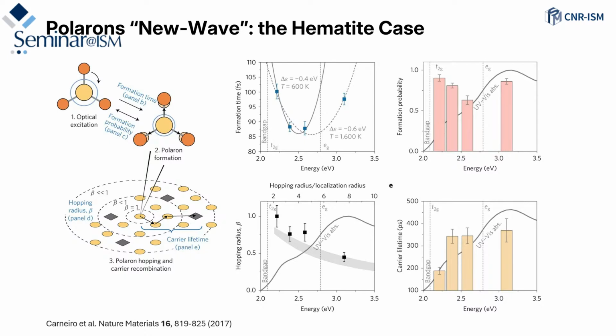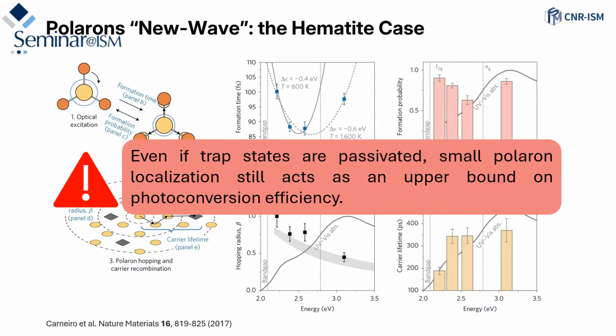Moreover, if you give more energy to those systems, you can have this hopping radius, which means that you make more hopping in the system, and also you have a longer carrier lifetime, considering when you pump just the transition. But what I want to give you as a final message of this paper is that even if the trap states in those systems, like the surface of the transition metal oxide, are passivated, the small polaron localization is just the upper bound for the efficiency of conversion of the solar energy.